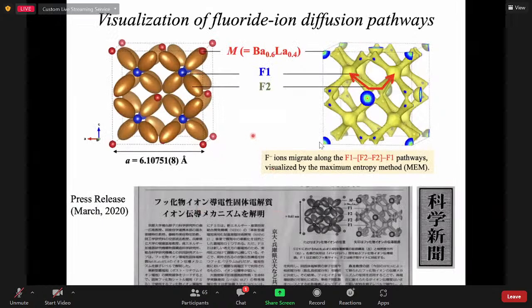And furthermore, I tried to visualize the diffusion pathway of the fluoride ion through the maximum entropy method, which is called MEM. The connected yellow area displays the nuclear density. The connected area would carry the fluoride ion from one site to another. That's why we conclude that the fluoride ion migrates along the F1, F2, and F1 pathway. Fortunately, the findings of this study were reported in the Japanese press in 2020. I was very happy.